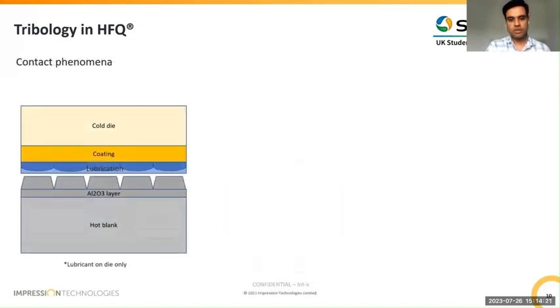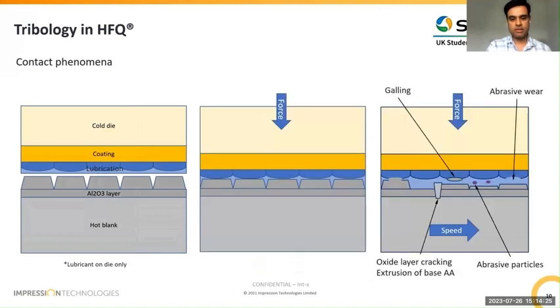And so what happens on a micro scale is what I've tried to explain here. So talking from left to right, you have only one side of the contact. So there's an aluminium oxide layer. So imagine if an aluminium blank is being solution heat treated, then there's an oxide layer growth that is happening. And then that layer is also porous. When the die comes in contact with the aluminium blank, which is not lubricated, then there's an exchange of lubrication.